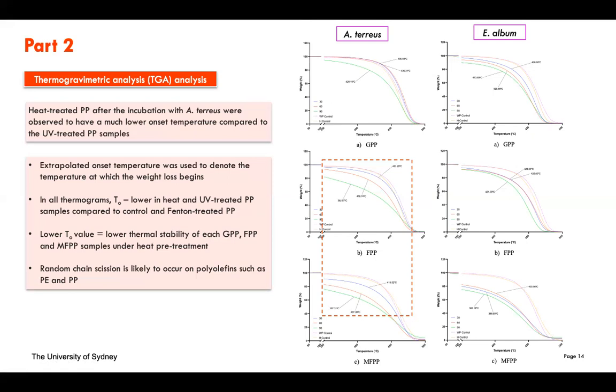So in a way, we know that after the incubation with the fungi, they are able to cause some kind of chain scission on the polymer, which is likely to occur also on other types of polyolefins, such as polyethylene, right? So we want this to happen. A much lower onset temperature, as you can see from the reduction here, indicated the degradation of the polymer by the fungi. Right.